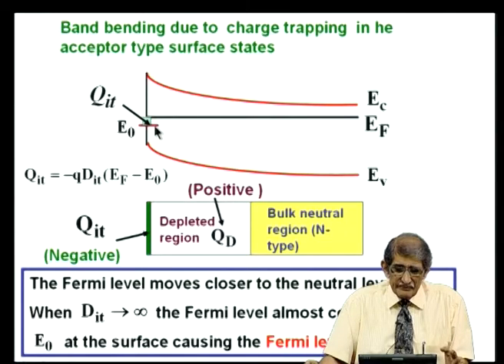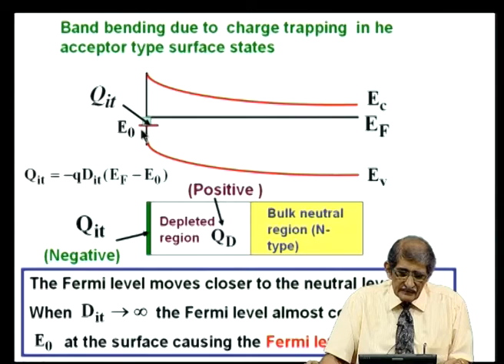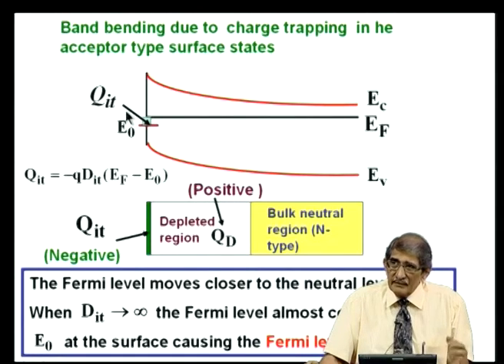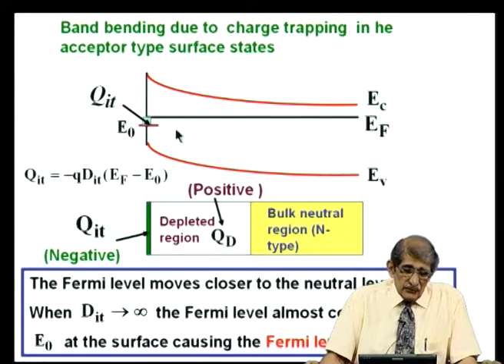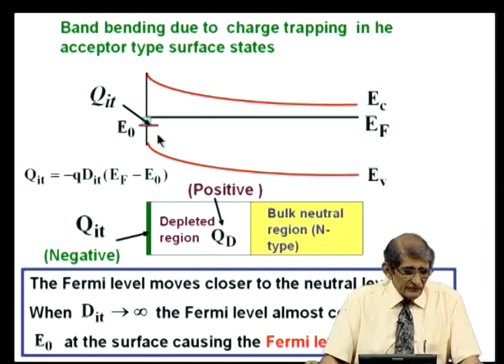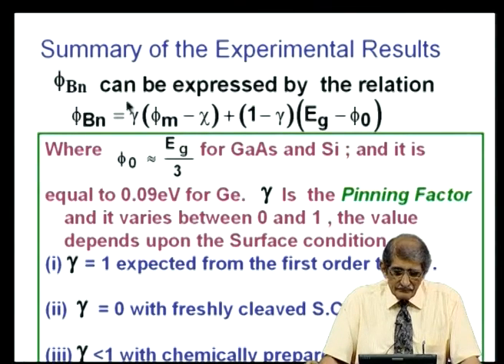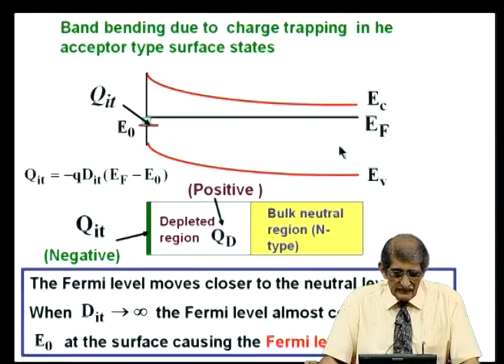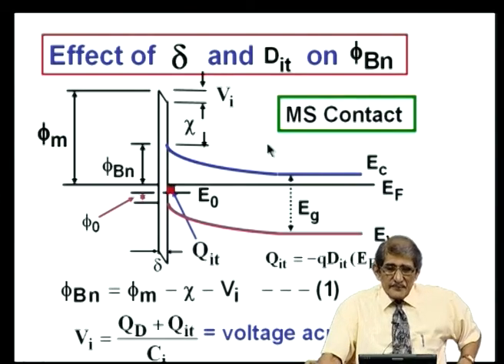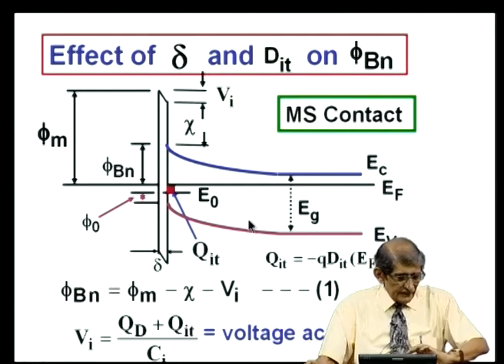So, if the Fermi level is pinned, you can see that this is coinciding with that. And the gap between the top layer and this Fermi level is phi b n when I put a metal. Now, that particular formula that we have put there has been derived way back in the 1960s and still holds good. Cowley and Sze derived that equation using the assumption that, in the derivation, I will just quickly run through that.